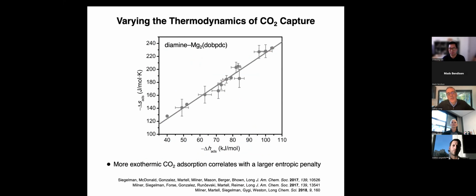And so here is a plot just showing the thermodynamics and how in this inexpensive magnesium-based MOF, just changing the appended diamine will vary the delta H and delta S of CO2 adsorption. And so there's a dozen or so different diamines appended to that same base MOF. And you can see, you can change delta H from anywhere from minus 40 kilojoules per mole to out past minus 100 kilojoules per mole. And as you do that, as you increase the enthalpic driving force for polymerization, at the same time, you're making more and more tightly wound chains, and you're paying a larger and larger entropic penalty. And so our adsorbents tend to fall along this master line, the gray line.